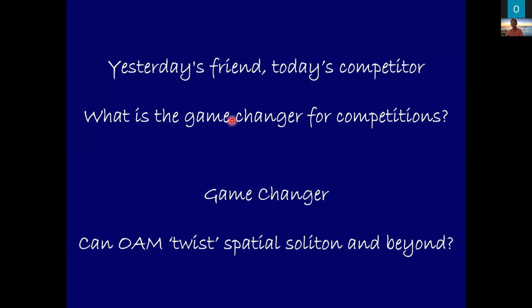At this moment, I would like to show you one game changer for such a competition. What is a game changer? We want to think about orbital angular momentum together with the spatial soliton and beyond. Okay? We performed the experiment by using optical illumination. At that moment, we can control the morphology of the surface of the matter, but the inside of the material doesn't care. But if we combine the spatial solitary effect and orbital angular momentum, we can directly control the morphology of the inside of the matter. Okay, this must be the three-dimensional structured matter formed by the orbital angular momentum transfer effect.